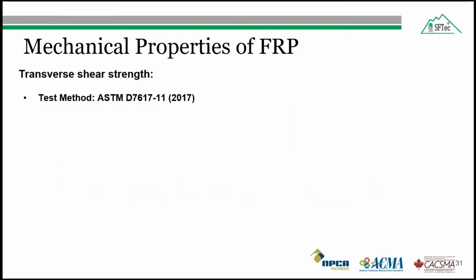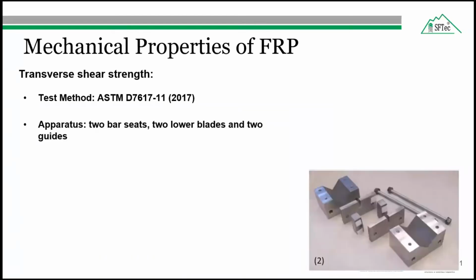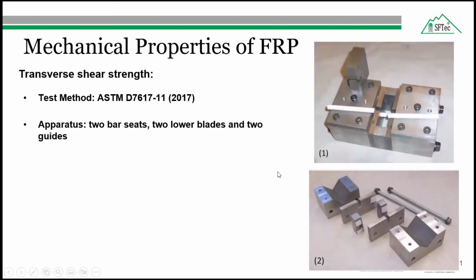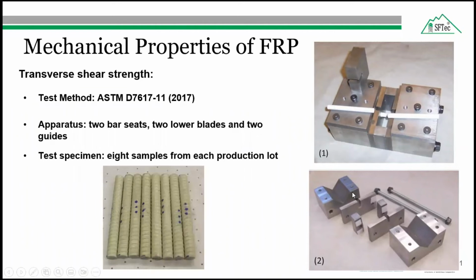So the next test in this category is the transverse shear strength of the FRP specimen, which was conducted in accordance with ASTM D7617. And the test apparatus, as shown in the figure, consists of two bar seats, two lower blades, and two guides machined from steel. And these parts were bolted together with two threaded rods, washers, and nuts, as shown in this figure. And the upper plate was kept loose so that we can put the samples inside, and it was fitted just before starting the test.